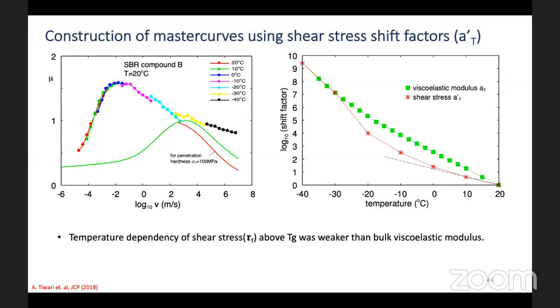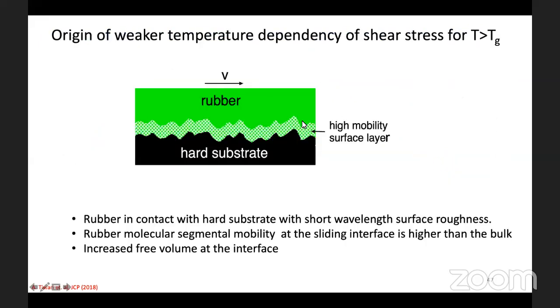Adhesive contribution basically takes place at the surface, and this is where the rubber patches bind and then do cyclic stick-slip. So it has a weaker temperature dependency as compared to the bulk of the rubber. Why there is a weaker temperature dependency can be explained by the fact that when you have a rubber sliding on a hard substrate, because of short wavelength surface roughness, there is a region of high chain mobility at the interface, and that has low energy barriers